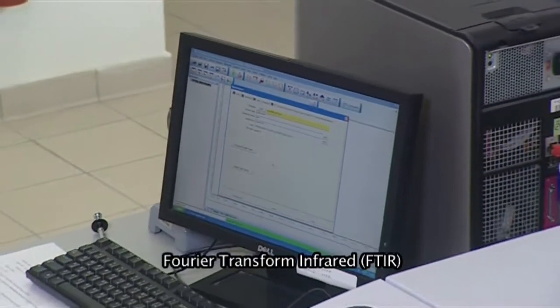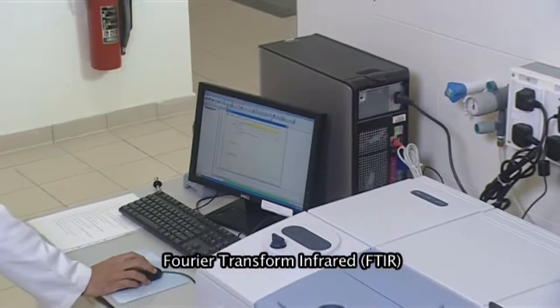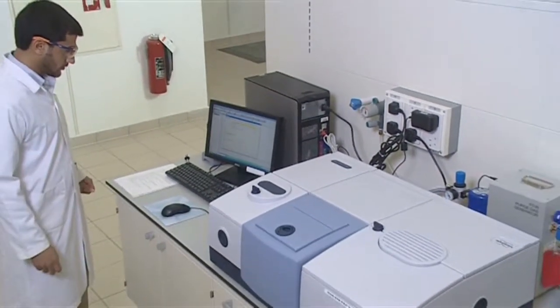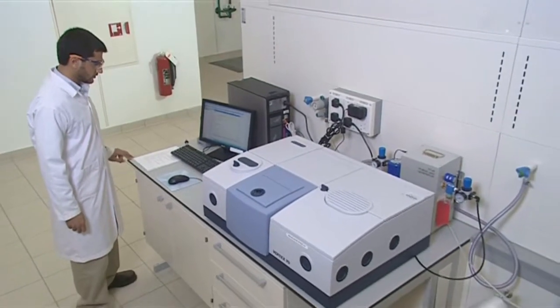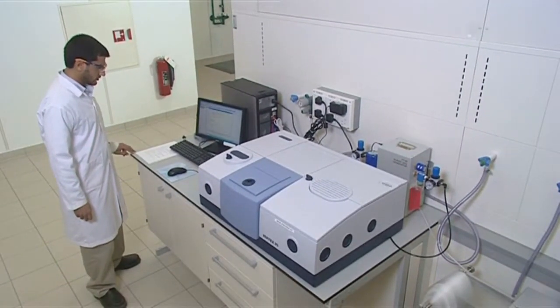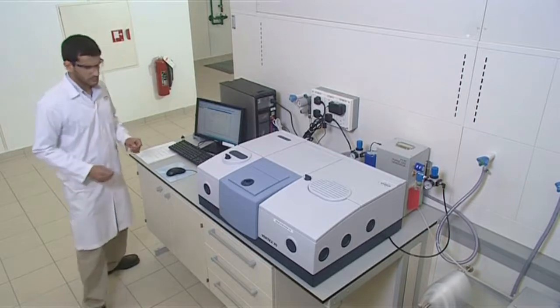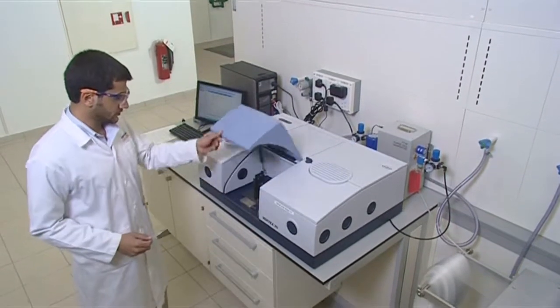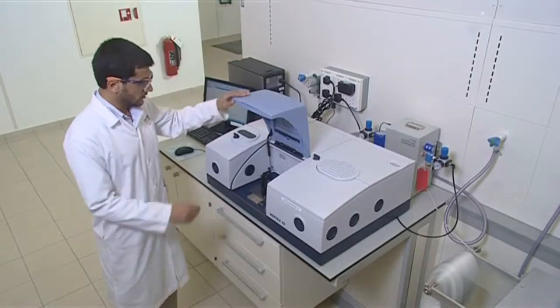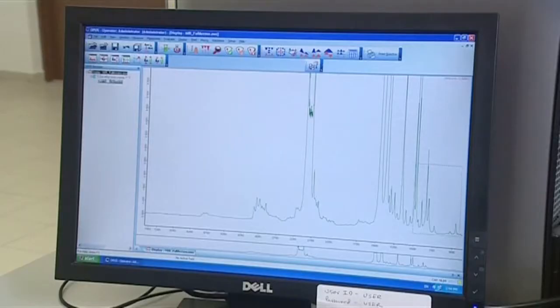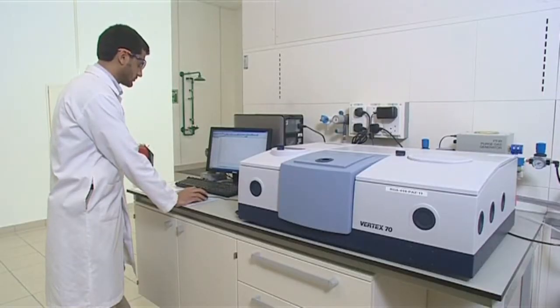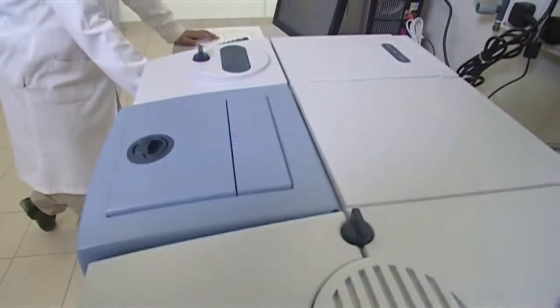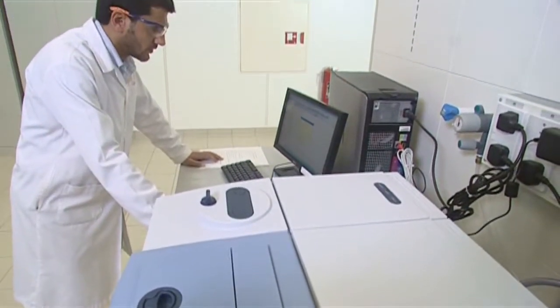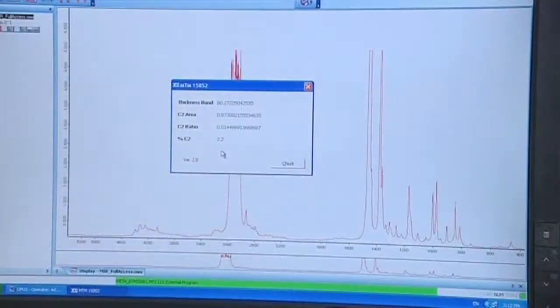Fourier Transform Infrared, FTIR, the preferred technique in polymer industries, is the fastest and precise technique to identify certain additives in the polymers. This is the best technique to identify the unknown materials qualitatively as well as quantitatively. In Saudi Kayan, it is used mainly to analyze the copolymer concentration in the polypropylene impact and random grades. This is the only fast and precise technique to monitor the bonded C2 in copolymer.